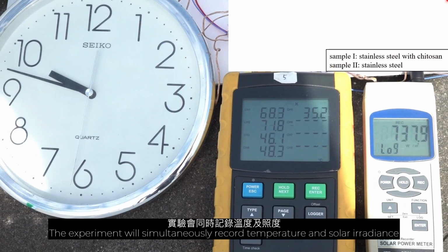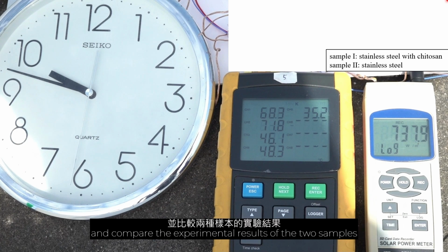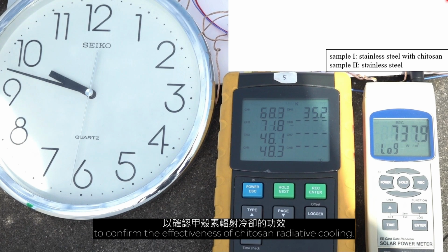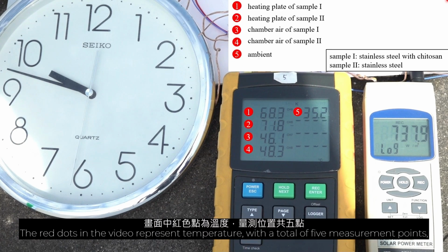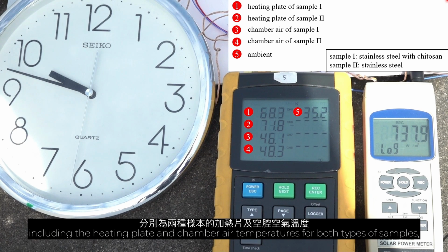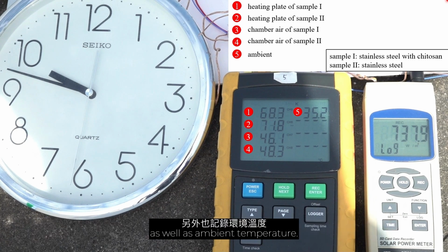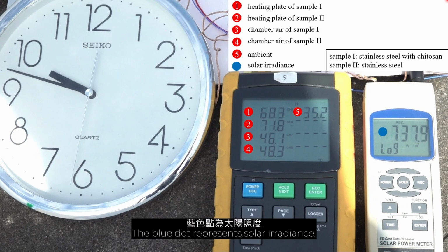The experiment will simultaneously record temperature and solar irradiance and compare the experimental results of the two samples to confirm the effectiveness of chitosan radiative cooling. The red dots in the video represent temperature, with a total of 5 measurement points, including the heating plate and chamber air temperatures for both types of samples, as well as ambient temperature. The blue dot represents solar irradiance.